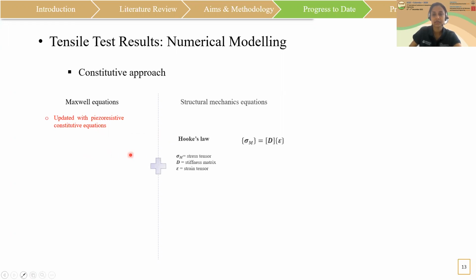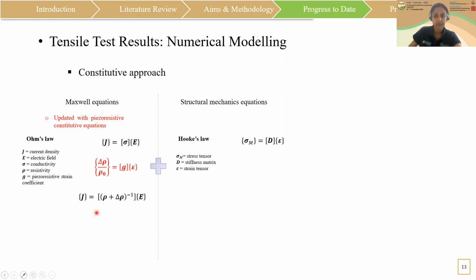So to interpret the tensile test results from a macroscopic point of view, a constitutive approach is used by coupling Maxwell equations, which are updated with piezoresistive constitutive equations and structural mechanics equations as follows. The general Ohm's law is updated by the piezoresistive conditions to obtain the following updated Ohm's law for piezoresistive materials. And the piezoresistive equations relate the induced strain to the relative change in resistivity using the piezoresistive strain coefficient G.